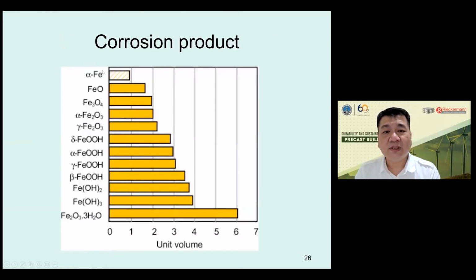And when the corrosion is occurring, the steel will expand. The expansion is due to the change of phase in the material. Normally it will change into ferric oxide, and the rust that you normally see with the red color is Fe2O3 with water, and it has 6 times the volume. So 1 millimeter of the steel reinforcement that is corroded can change to 6 millimeters. So it expands so much.